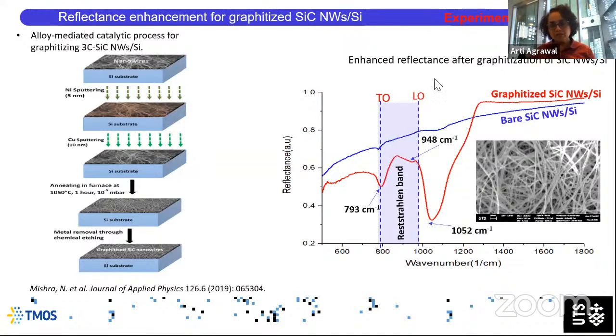If you look at the reflectance of this structure, the bare silicon carbide nanowires give you the blue reflectance curve. But as soon as you look at this random nanowire structure, you get the red reflectance curve. So you have a prominent dip at about 1050 centimeter inverse and a dip at about 793, or close to 800 centimeter inverse. And the reflectance is high in between, which is inside the Reststrahlen band. So obviously, as soon as you graphitize the nanowire, its behavior changes substantially from blue to red. And that's where the interesting features lie.